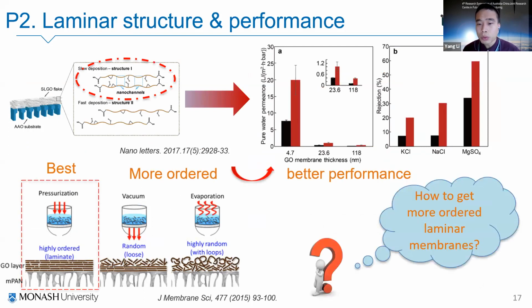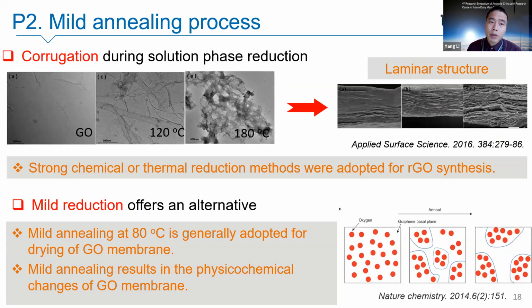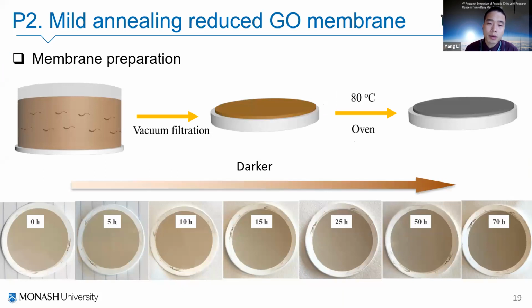So one thing we can do is to prepare more ordered laminar channels. From the previous study, we know corrugation happens during the solution phase reduction, which results in different laminar structures. And mild annealing at 80 degrees is generally adopted for drying. However, it has been proved to be effective to produce reduced graphene oxide materials. So how about mild annealing for thermally reduced graphene oxide membrane preparation? Here is the method we developed for this membrane.